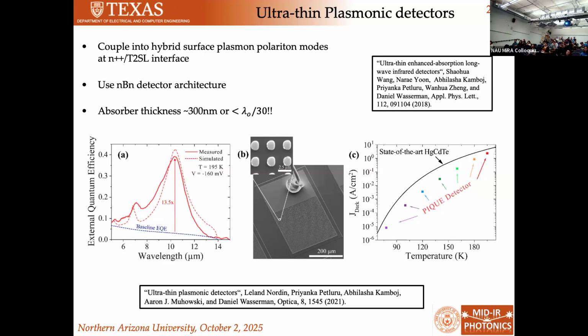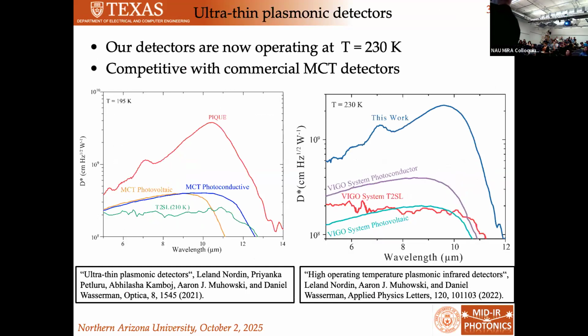This is a detector that's only about 300 nanometers thick, and it's absorbing light at 10 microns. Typically, a detector that's operating at 10 microns would be on the order of 5 to 10 microns thick, right? So we've reduced the thickness of this detector by over an order of magnitude, and therefore our noise will go down as well. And in fact, you can see this is the state of the art, or it was the state of the art for mercury cadmium telluride detectors, which are the standard for mid-infrared detectors. And you can see our dark current is well below that. And in fact, what that means is that we can operate these detectors at higher temperature.